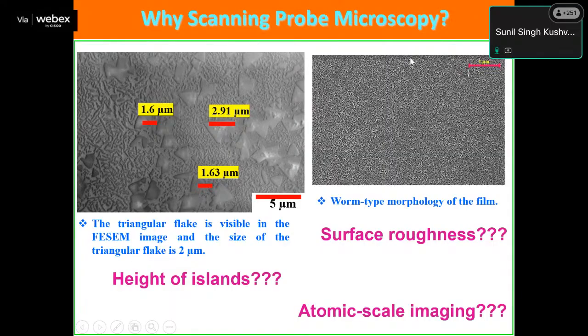Same thing if we have this worm type structure, we don't know the surface roughness. Is it 100 nanometer or 2 nanometer? And third, whether we can do atomic scale imaging. Of course, it is not possible because the SEM has a resolution of maybe 1 nanometer or 0.5 nanometer. That's the reason we have to move toward scanning probe microscopy, because SEM has two directional scanning, X and Y, but in scanning probe microscopy we can move in X, Y, and Z.